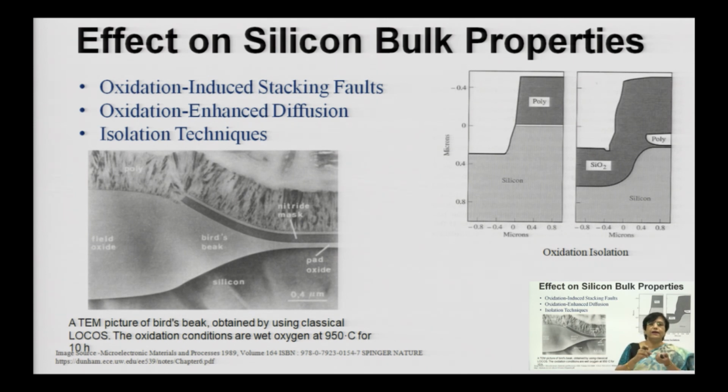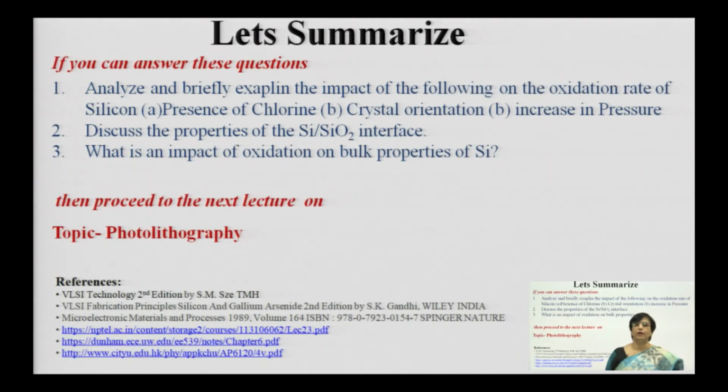Then the nitride layer is patterned and the unwanted portion is removed, then the oxidation is done, and that is how you will have beautiful isolation with a very thin film of oxide. Similarly, here a polysilicon layer is done initially, then it is etched away and the silicon dioxide is grown. So, here you will have a small active area where the polysilicon is, and the rest is insulated with the help of oxide.